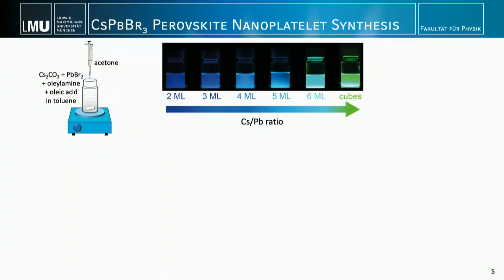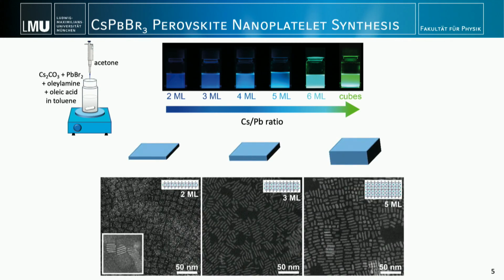So my colleagues and I came up with a synthesis routine where we have two precursors, one containing only cesium and one containing only lead. By playing with this ratio, we could then achieve, and this is what you see here in this nice picture, samples of different color. We have it from the dark blue range up to the green range, just by playing with this ratio. And electron microscopy could confirm these thicknesses.